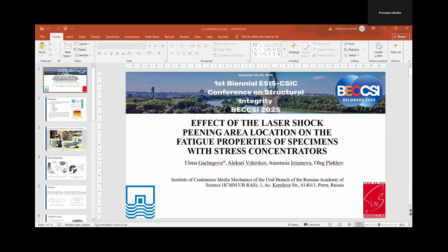And finally, the fatigue test results for these specimens from titanium grade 2. Analysis of this diagram showed that the first treatment scheme negatively impacted the fatigue properties of the V-shaped notch specimens, as the number of cycles to failure decreased by 30% compared to untreated specimens. And specimens treated with scheme 2 showed a roughly two-fold increase in fatigue life.